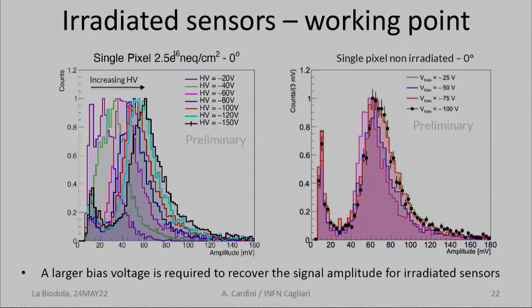So this is the Landau distribution of the irradiated sensor as a function of voltage, and this is the one of the non-irradiated pixel. You see that the Landau most probable value moves to the right while increasing high voltage. But what you can see is that at a bias voltage of the order of 100 volts or so, you are able practically to go back to the amplitude performance of the non-irradiated sensor.